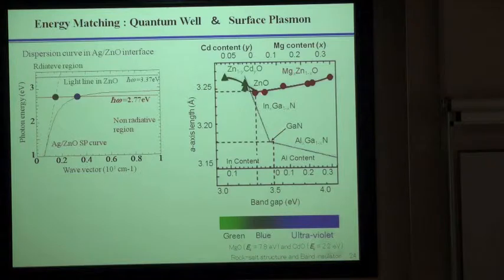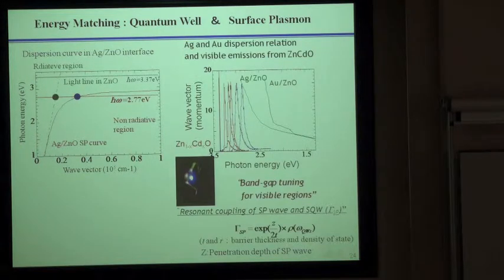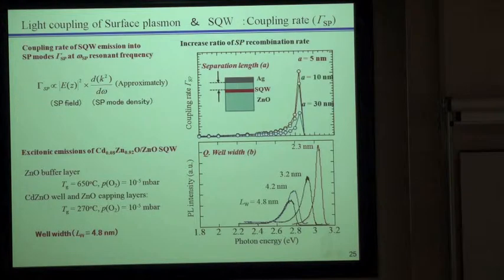To do that, we have to make cadmium doped zinc oxide systems. And fortunately, we successfully found that the band edge can be controlled by controlling the concentration of cadmium ions. So here is the pure zinc oxide, and with increasing cadmium concentration, the luminescence, so the band edge, here is the photoluminescence, comes down to 2.7 eV. Right here, there is a crossing point. It means that this information can be read out by using these devices.